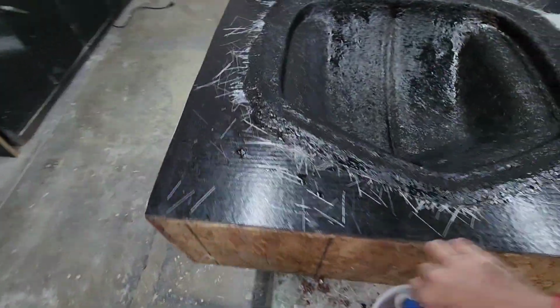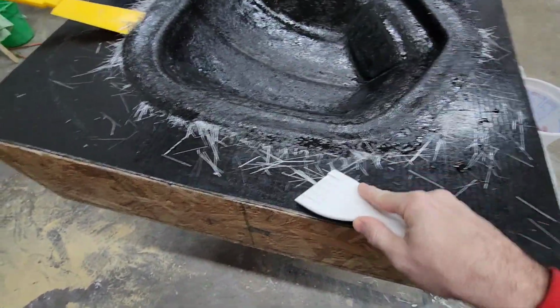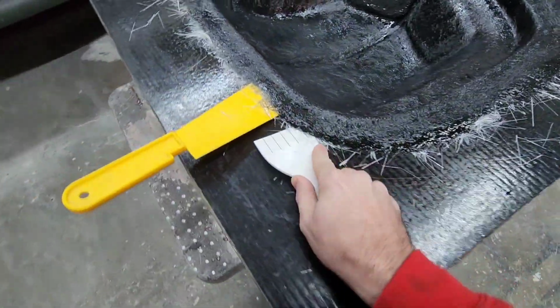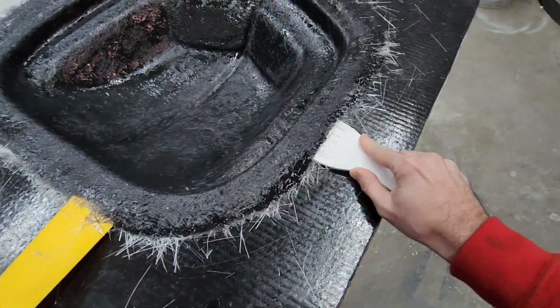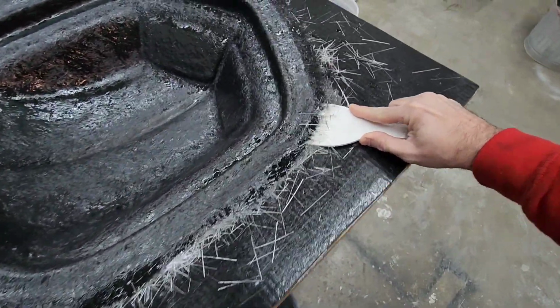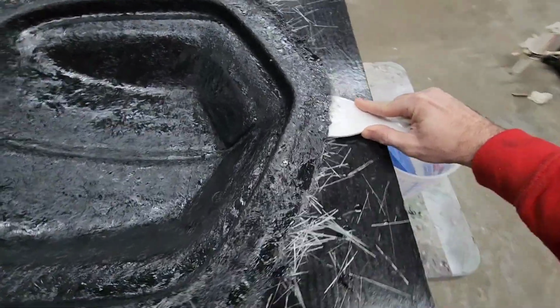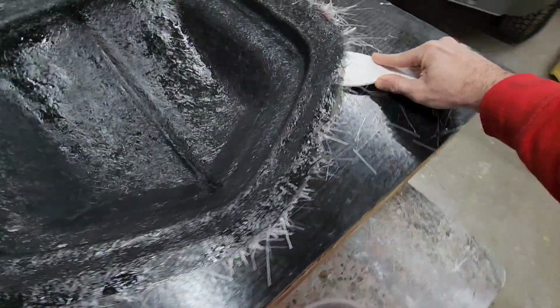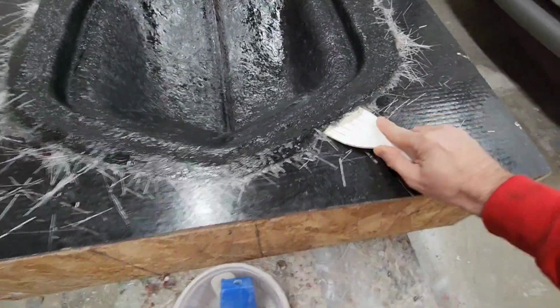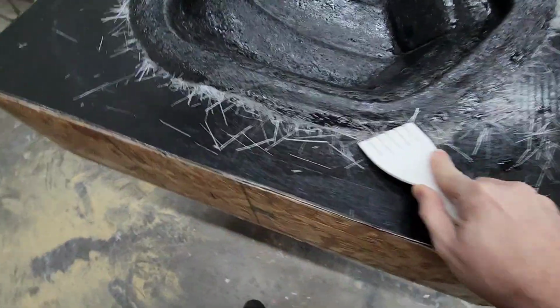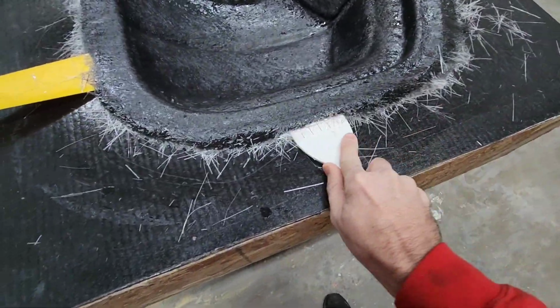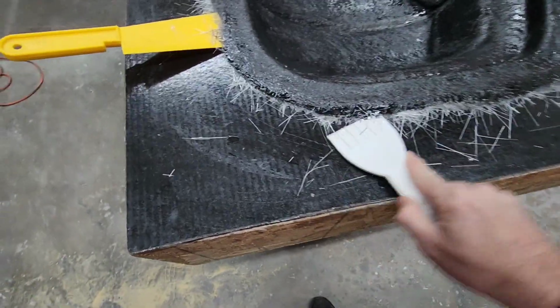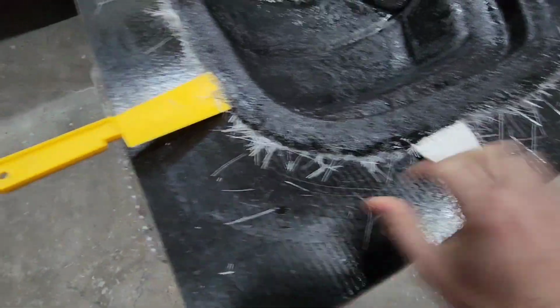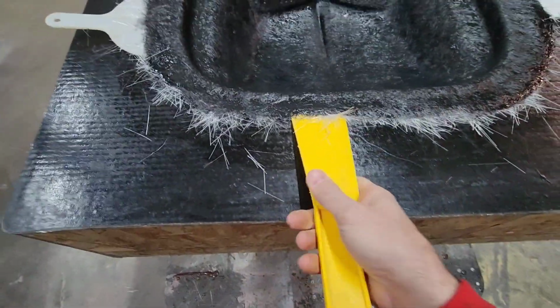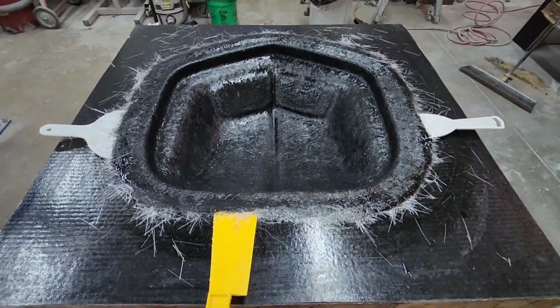Once I get this separated, and I think that the perimeter is breaking free here, then I'm just going to squirt a blast of air underneath. I should pop it the rest of the way out. All right. So that separated really nice, and that's because we did those wax layers and the PVA. So we've got a really nice flange separation.